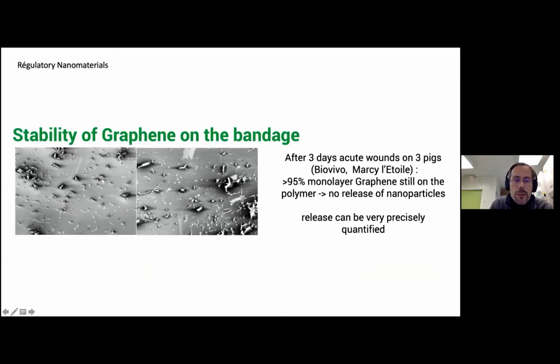So importantly, we have to check that the graphene on this material stays integral, that it's not leaching out nanoparticles. Here you see two micrographs taken on different places of the same bandage I've shown you before on a pig after 3 days. The scale of the graph here is about 20 microns. You clearly see that there is indeed a little bit of defect, the start of delamination because of the rubbing effect of the wound on the graphene, but very little amount is actually being released. It's less than 5% and it's a monolayer, so the quantity leaching out is extremely small, and actually it's probable that there is delamination but still no leaching of nanoparticles. But we can quantify that, very importantly, quite precisely because we know that there is only one monolayer on the